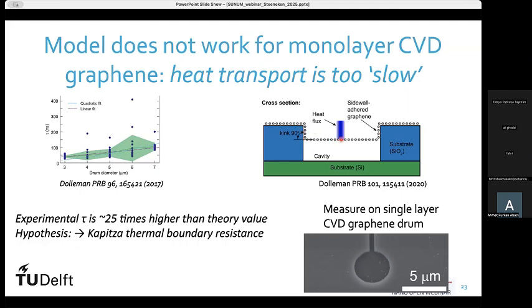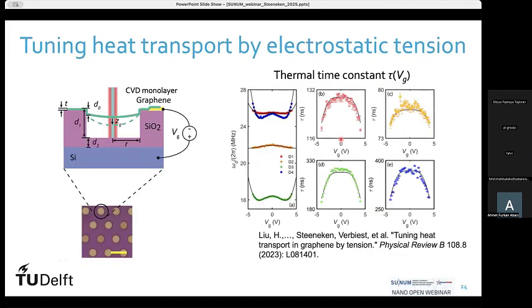As a consequence, heat that travels from the center of the graphene membrane to the edges finds a thermal impedance here, because part of these acoustic waves reflect from the edge instead of being transmitted to the supported part of the graphene. We also made a model which could explain this increased resistance. And this is probably why the thermal transport of a graphene membrane is much slower than you would expect purely based on its material properties.